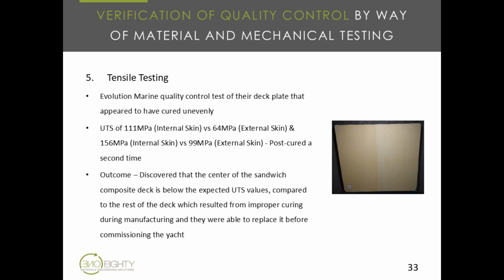So the outcome is that the center of the sandwich composite deck was below their expected UTS values because it cured improperly and there was an air bubble, which I'll show now. They didn't realize that the valve wasn't closed during curing, but they managed to pick this up. And because of that, they were able to, unfortunately, redo the whole thing. But rather that, a couple of thousands of rands replacement of the deck and redoing that, compared to a failure at sea of their clients, which could cause litigation in the end. And perhaps even loss of life.